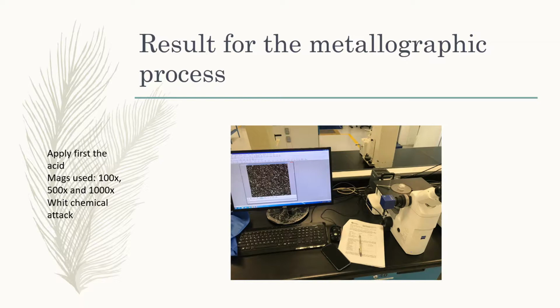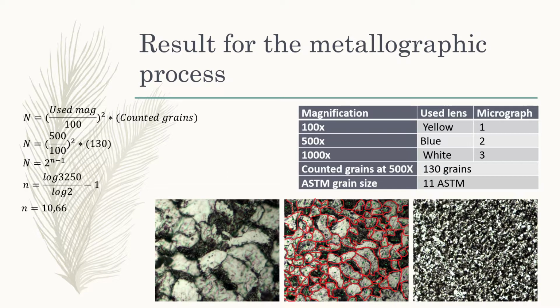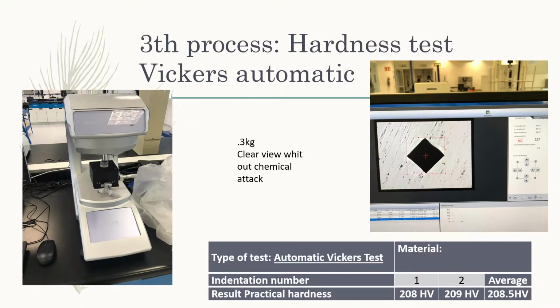Next, we put it in the microscope to see all the grains. We use magnifications of 100, 500 and 1000. We can see the results. In the first image is the 100 view, the next image is the 500 and the next the 1000. We do the analysis for the 500 and we can count 130 grains and an ASTM grain size of 11.